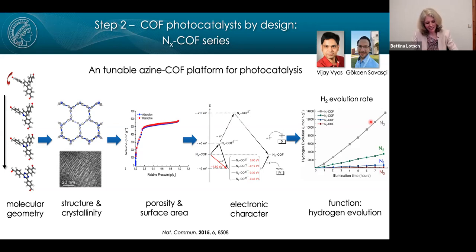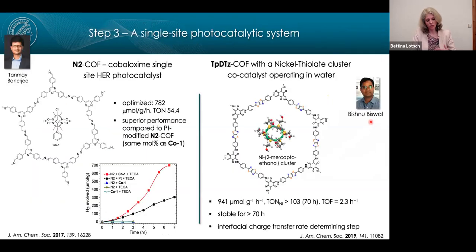So the next task basically was to get rid of the platinum co-catalyst and replace it ideally by something earth abundant and also by something molecular, so that we get better insights into the photocatalytic mechanism as such. And so a very brief summary here, if you're interested in that, of course, I'd be happy to discuss that after the talk. So our first attempt was basically to just hybridize the COFs with a molecular co-catalyst, a cobaloxime co-catalyst. These are very well-known electrocatalysts for the hydrogen evolution reaction.